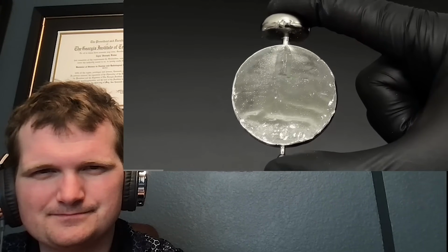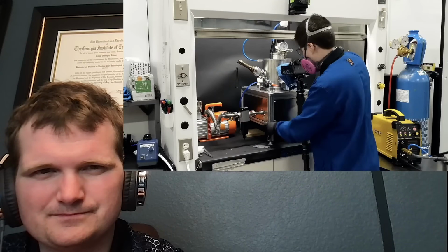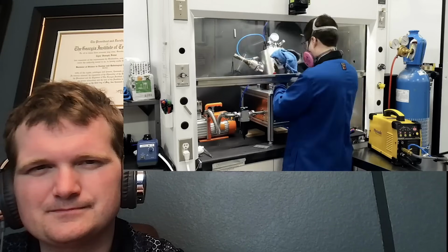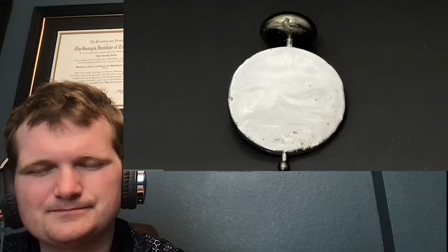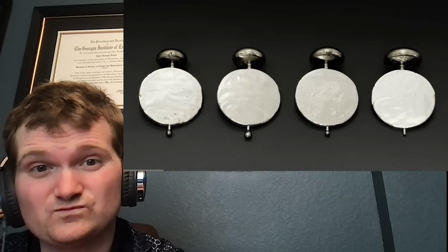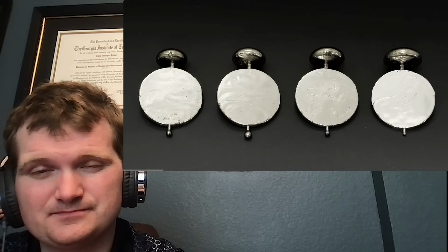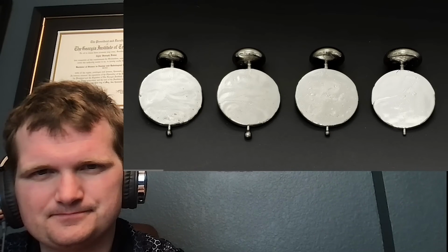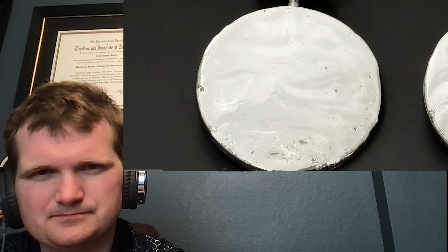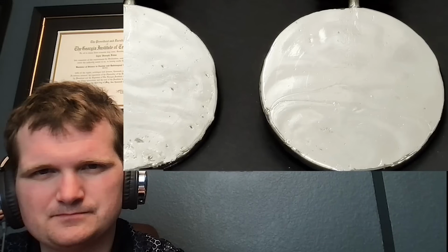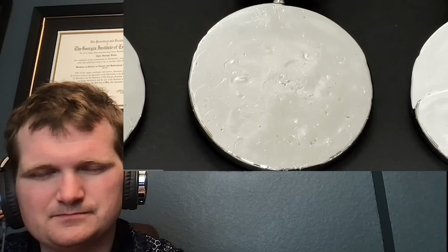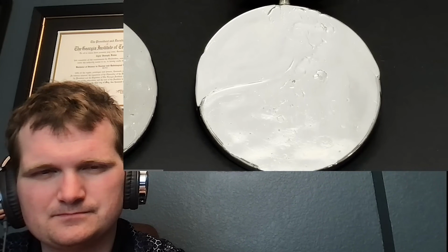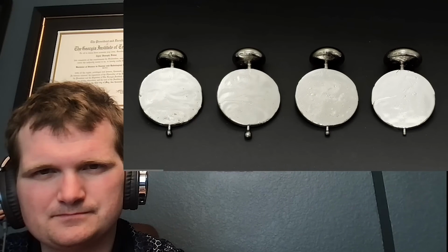With that being said, I then went ahead and did the exact same thing for all of the other ones, and a couple of them were still a bit finicky, but in the end, I was actually able to make 3 more discs. Like the first one though, none of them were quite perfect, and they all had some slight defects, and on the surface of them, they all looked like they had some weird ripples. However, from what I could tell, this was extremely minor, and it only seemed to be visible because they were so shiny, and overall, I still felt that they were more than good enough.